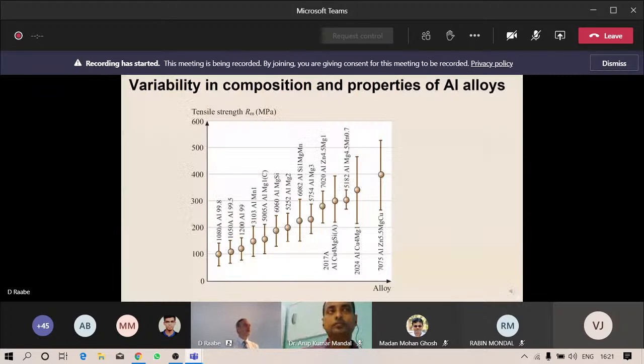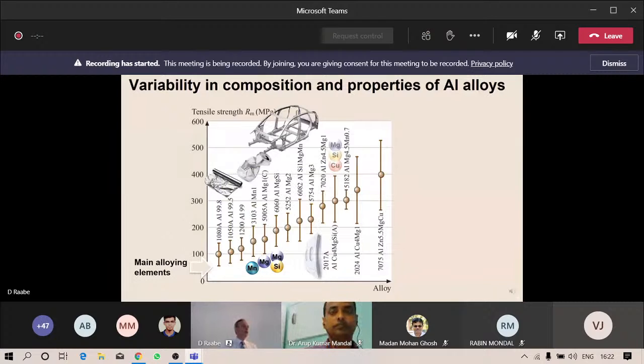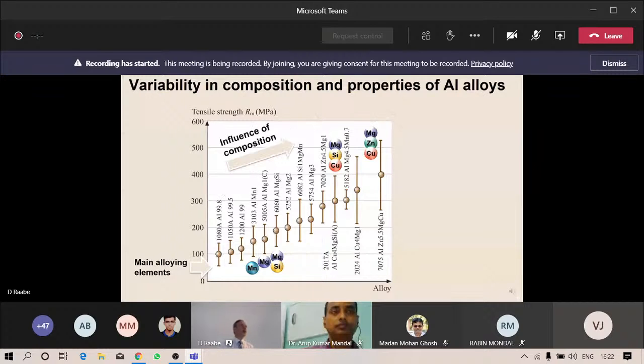Let me show you just a little appetizer, a little example here related to the field of aluminum alloys. On the left-hand side, you see the tensile strength plotted against the alloy families. So you're all aware of these many alloy families that we use in the field of aluminum, from packaging towards automotive engineering, aerospace engineering, mobile communication, and so on. And I also plotted here additionally the main alloying elements that are exploited in these respective alloy families. And we see that there's a substantial influence, of course, of the composition, typically turned into nanoprecipitates in such aluminum alloys.